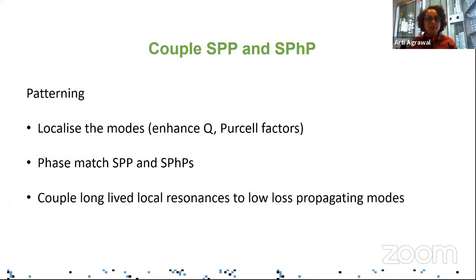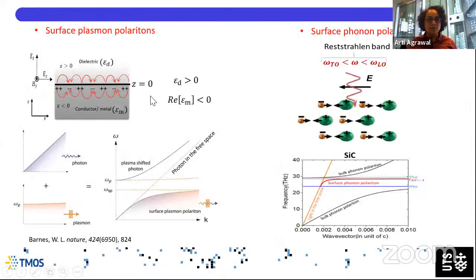So one of the things that we are planning to do is to use coupling of SPP and SPHP by patterning. So by patterning, what we intend to do is to localize the modes and enhance Q factors, Purcell factors, etc. for nonlinear applications. And apart from localizing, what the patterning does is to also enable us to phase match the two different modes and to have a transfer of momentum between them. It also allows us to couple long-lived local resonances to low loss propagating modes. So here is just a schematic showing you surface plasmon polaritons and surface phonon polaritons. But since I've already explained this, I'll move on to the next slide.